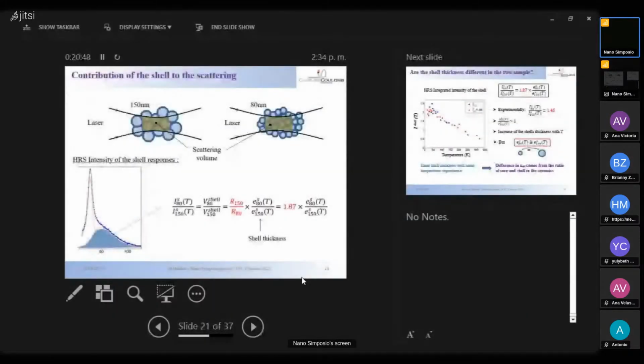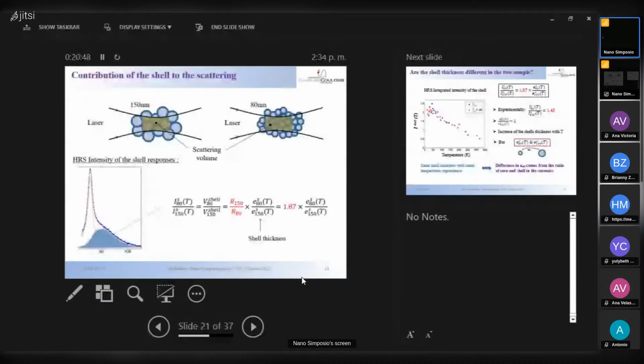This just corresponds to the amount. So if you calculate the ratio between the intensity of the small grain to the large grain size, you end up with this, which is a constant 1.87 times the thickness of the shell for the ceramics with 80 nanometers grain size over the thickness of the shell of the large grain size ceramic.